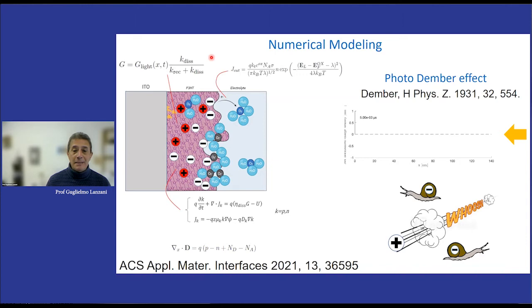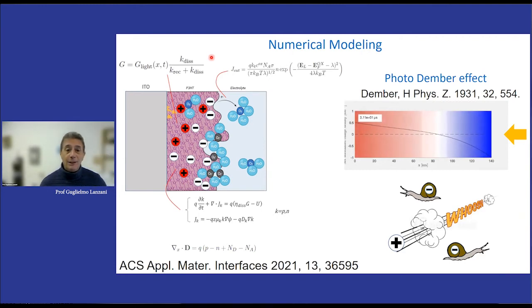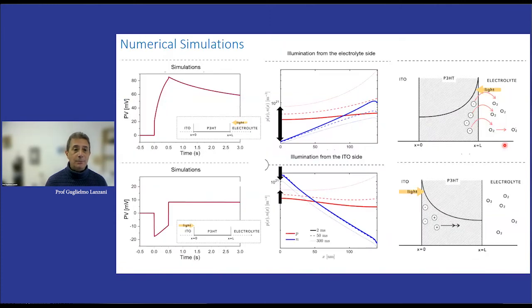Because there is this imbalance in the transport property and the negative charge does not move, the result of the photoexcitation is a polarization of the field, because the positive charge is spreading around while the negative charge does not move. And you see here that negative charge, blue, remains, while red, the positive charge, is building up on the rest of the movie. So if you sit here with your electrode and you illuminate on the other side, you will find a positive signal. If you illuminate the other way around, in other terms, if you read on this side, of course, you will read a negative photovoltage. And that's what our simulation is reproducing very well.